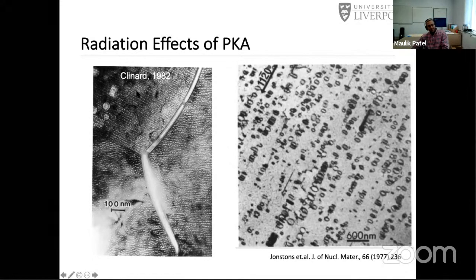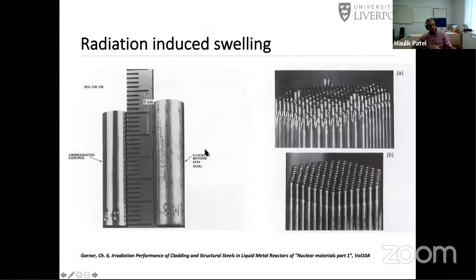And if you take good TEM micrographs, with an electron microscope, you can actually observe these white spots that look like bubbles, which are actually vacancy loops in sapphire, in alumina. And then these are your dislocation loops in iron, essentially steel. And these lead to actually macroscopic growth of materials. So here you have on the left-hand side a rod of a certain length before it was used in a reactor, and after it was irradiated with neutrons in a reactor for a certain amount of time.